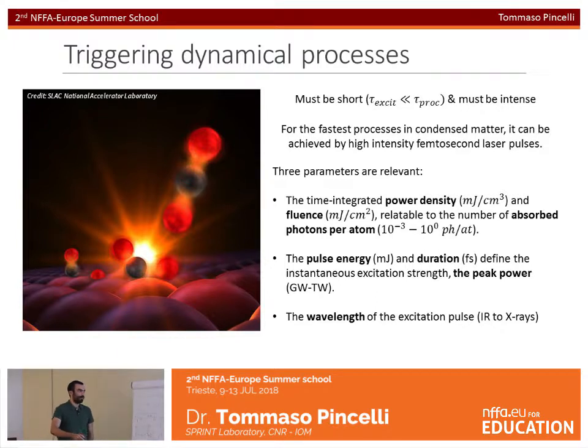And then, also very important, the pulse energy and the duration of the pulse, that together define the peak power that we reach. Because the de-excitation processes will start immediately after we have created the non-equilibrium configuration, we have to know what was the peak power that we sent on the sample, and thus how far from equilibrium we have set the sample. So in a very short time and with a very large number of photons per atom. And this can be in the gigawatt to terawatt range with short pulsed lasers.